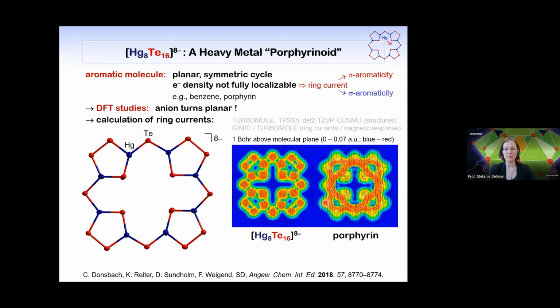And you see the difference. Very obviously, the porphyrin has a nice ring current going on, 1 Bohr above the molecular plane, while in this molecule, you don't find a really global ring current. What you find here is a weak local ring current, but it's in the sigma planes. And the reason for it is very simple, because we have much more electrons here. So this molecule is fully saturated, and it's not really fair to look after aromaticity in a saturated molecule. Yet we learned a lot during this chemistry.